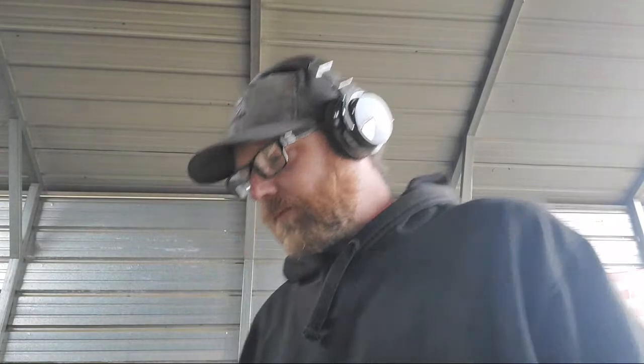I use brine for W1. For all my W1 knives with hamons on them, I'll show you the brine. I super saturate water with salt. Super saturated means you boil water and pour so much salt in it that it will no longer dissolve. No matter how long it boils, you're going to have salt sitting at the bottom of the pot still. That's when you know your water is completely salinated. Then add maybe a tablespoon of Dawn dish soap to that, and what that does is break down the surface tension of the water. And it's a really quick quench.